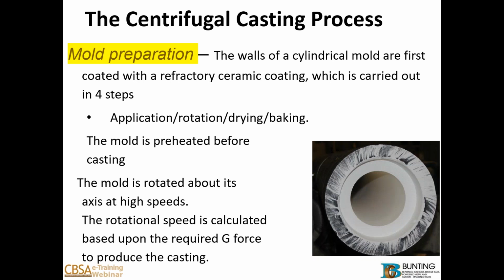Mold preparation. We clearly have a die that we're going to use. Keep in mind we're pouring very hot molten metal into either a graphite or metal die. So one of the things we need to do is make sure that the metal, the bronze in this case, doesn't stick to the die. So the walls of the centrifugal mold are first coated with a refractory ceramic coating, which is carried out in basically 4 steps. We apply it, we rotate it, it dries, and then we bake it so it's hot. So you see the whites in that picture, that's the refractory on top of the steel in this case. So the mold is then preheated for casting. So the mold is rotated, keeps it warm, and in that process, we start to calculate, or it's already been predetermined, how fast we're going to run that mold to produce the next casting. And we'll talk about that next slide.